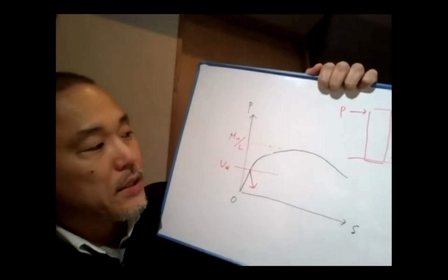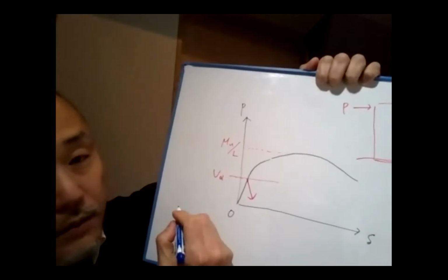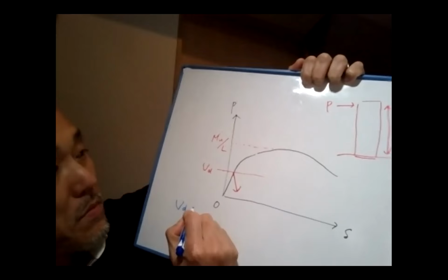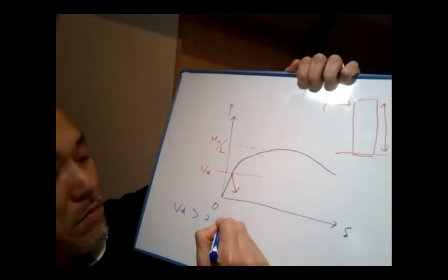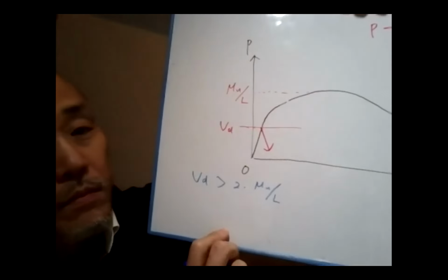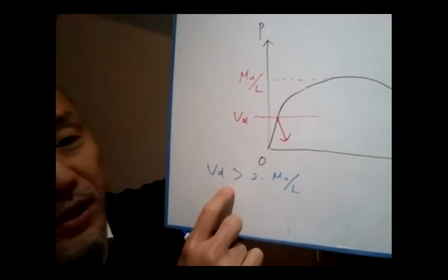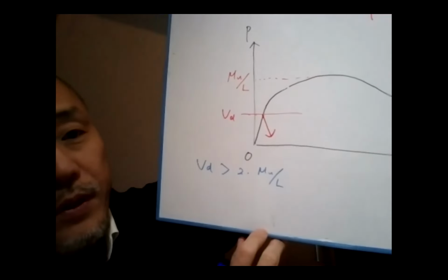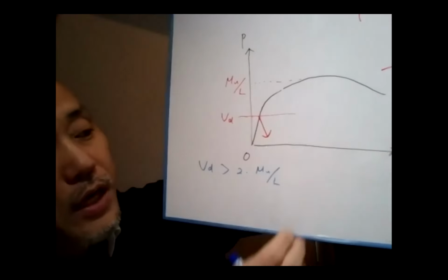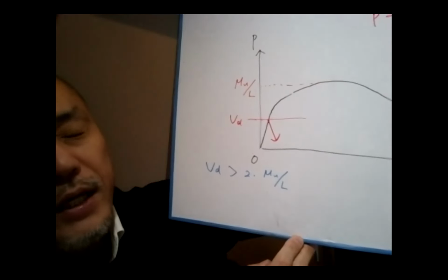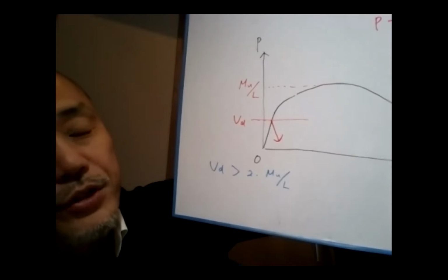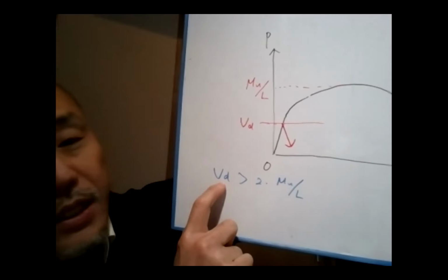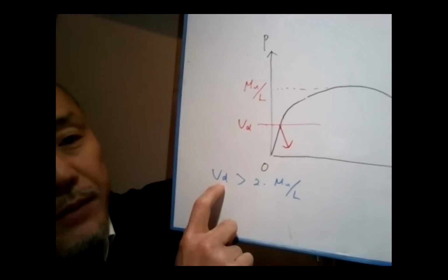So then, it's experimentally verified that if shear capacity is larger than the double of this shear force, then ductility will become very large. For example, 10 delta y etc. It's experimentally known. If you search papers, you can find. So here, what I want to say is that shear capacity should be sufficiently large enough.